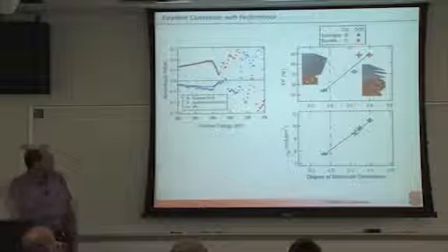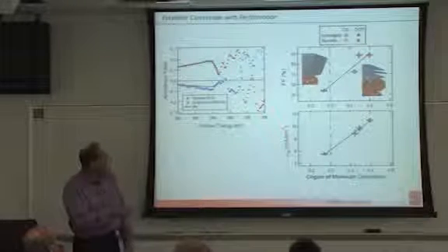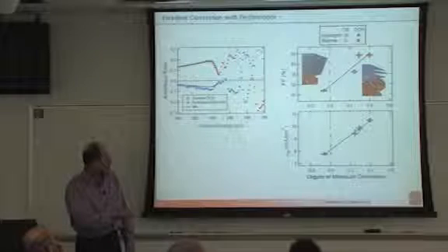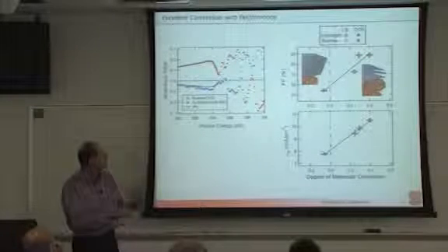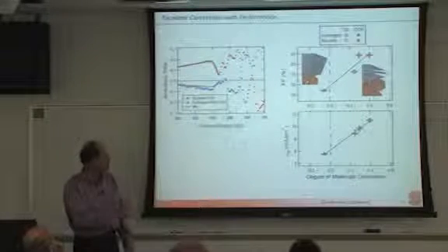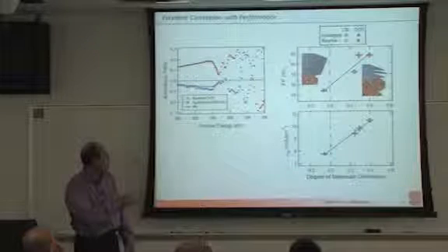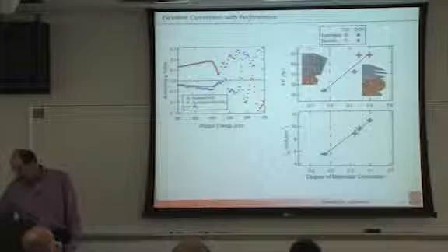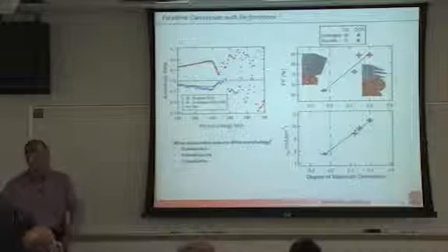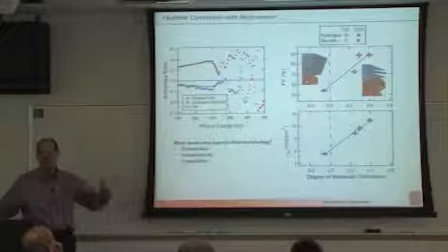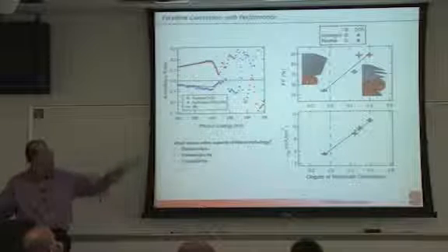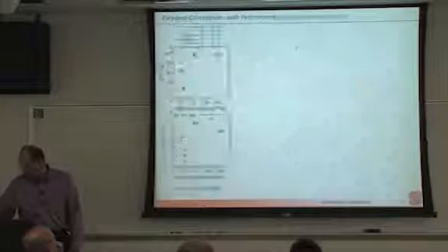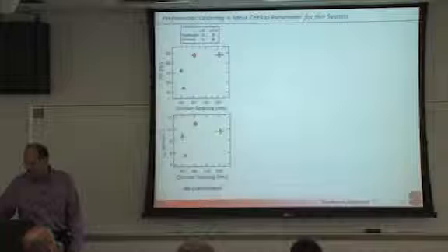We quantify this degree of molecular orientation and we get very good correlation. That's essentially the anisotropy parameter normalized through a model, for the JSC and the fill factor. Okay, but how about the rest of the things? Crystallinity, domain size, domain purity, you know, fine, you got a correlation, but are there other things that correlate?